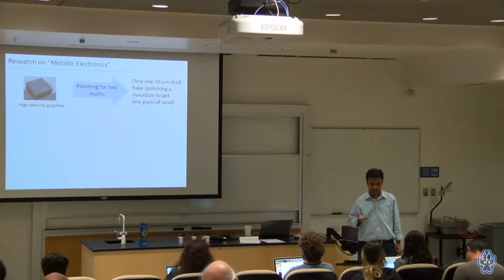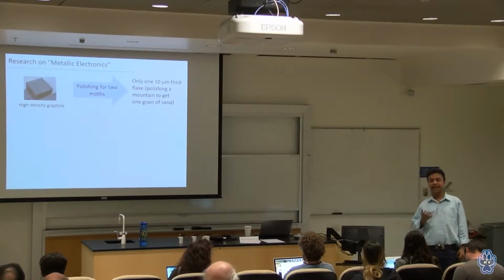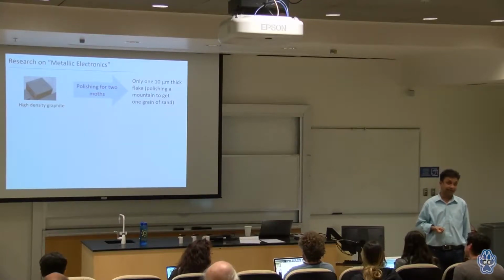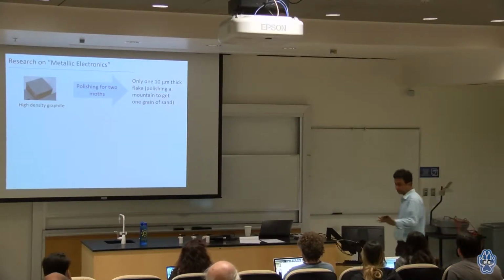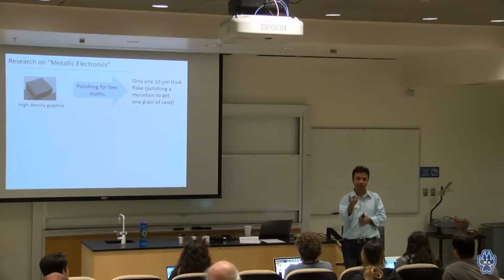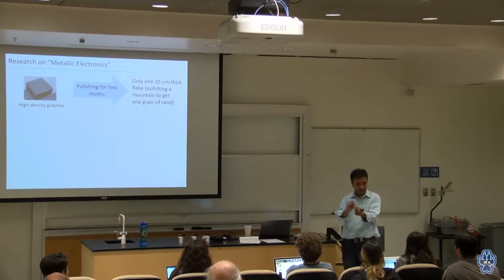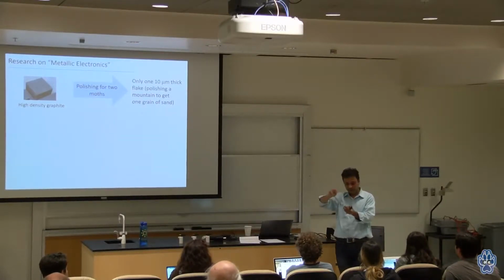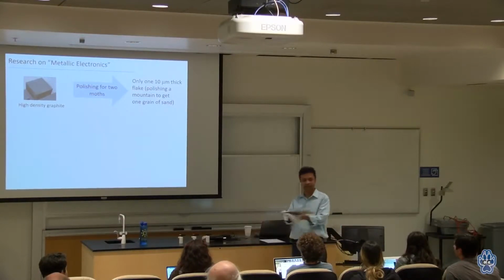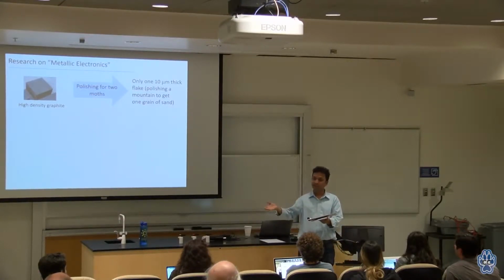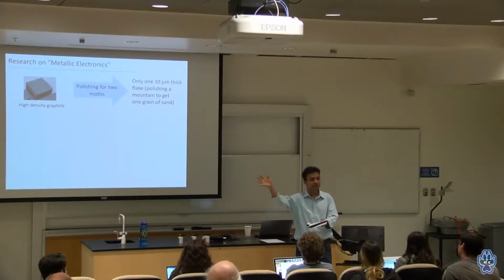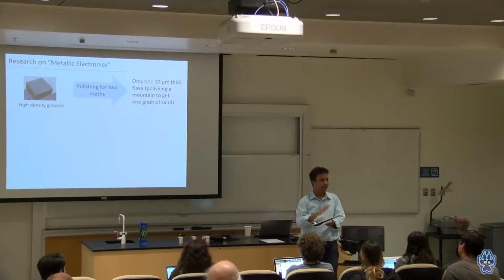They were listening to their discussion, and he was a scanning tunneling microscope specialist. If you know the scanning tunneling microscope, they use graphite as a standard sample, and they use Scotch tape to clean it. You start with a graphite, and you have this sample sit in your box. Over time, it will accumulate lots of junk. So they put a Scotch tape on and remove it to expose the fresh surface, so that you can have an extremely clean surface.